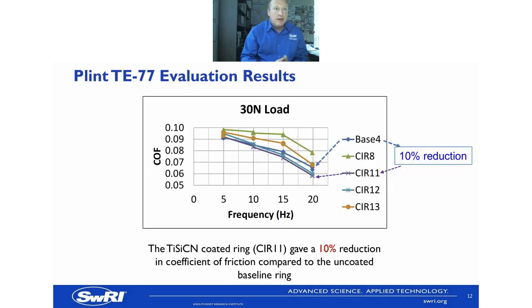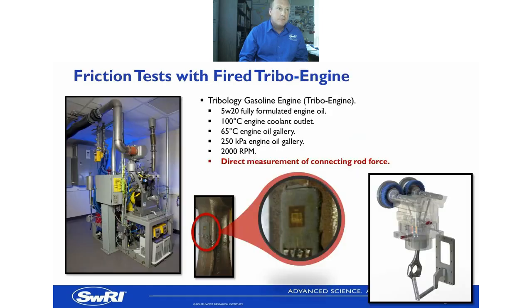And what we did is we had our original coating, which we're calling base 4 on this graph. And I haven't put all 12 on there because you can't differentiate between the lines if I do that, but I've just put some example ones on. So some of them you can see increased in friction and some of them decreased in friction. And the CIR11 coating that we developed actually gave us a 10% reduction in friction at that 20 hertz position. And so that's the one that we then took and we worked further with that one.